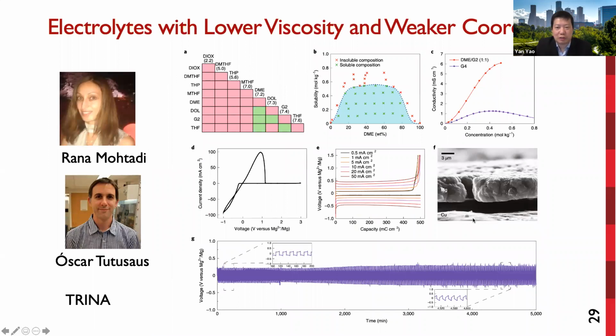While the fast kinetics has been shown earlier, the cell power is still limited by the mass transport in the MMC G4 electrolyte. So Rana and Oscar from Toyota tried a variety of solvent blends and found several mixed solvents provide much better solubility. Here we use DME and G2 as a mixture, which provides the best solubility, reaching a 6-fold increase in ionic conductivity. We have observed a mixed solvent shell of magnesium from NMR studies here. Cyclic voltammetry shows a 99.9% Coulombic efficiency, reaching an impressive 100 milliamp per centimeter square. So this is 10 times higher than that of MMC G4 electrolyte.